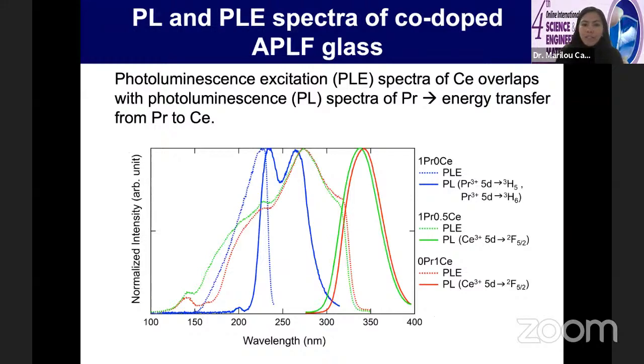Looking at the emission of our co-doped glass scintillator. This solid blue line shows the photoluminescence emission from the praseodymium ions when they are excited by the wavelength shown by this photoluminescence excitation curve. So the solid line is the luminescence emission. The dashed curve shows the excitation spectrum.